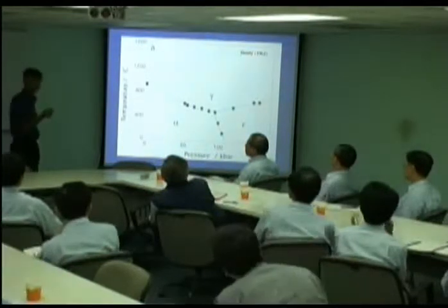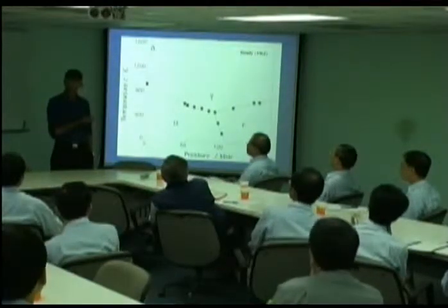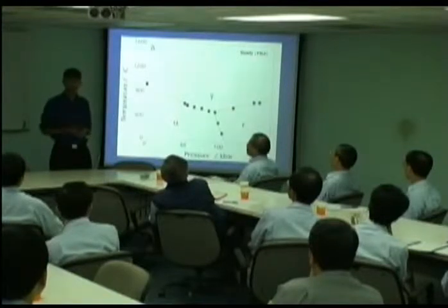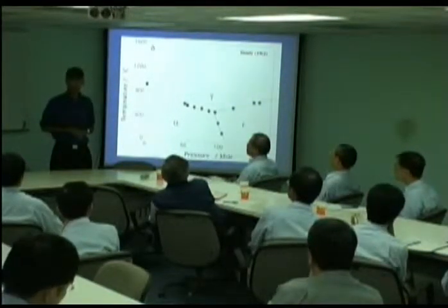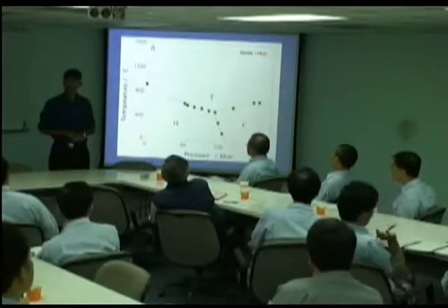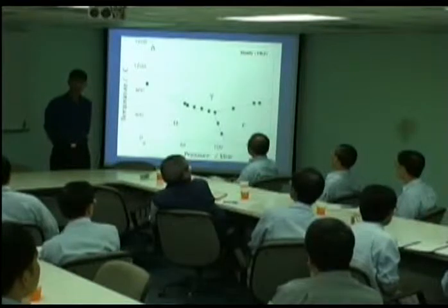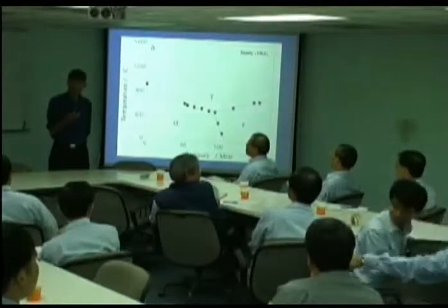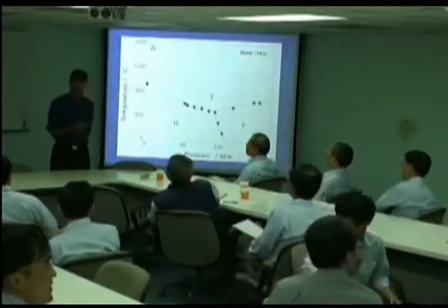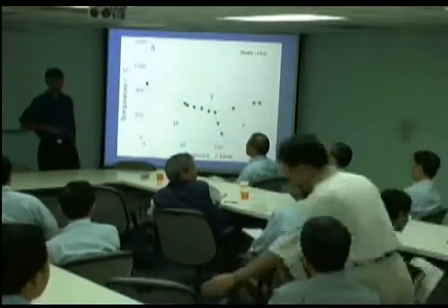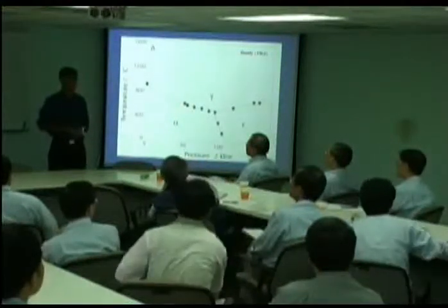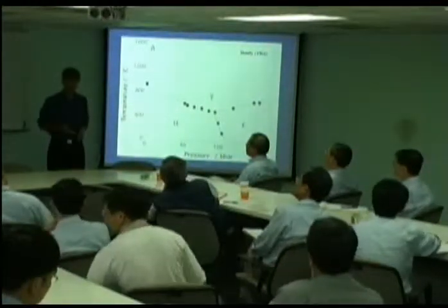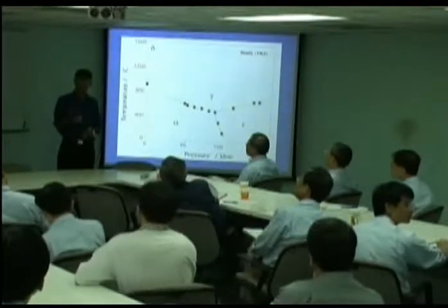So without adding any alloying elements at all, we have three different crystal structures, and each of these crystal structures has very important magnetic transformations in them. If those magnetic transformations didn't exist, then we wouldn't have ferrite at room temperature. We would have hexagonal close-packed iron, and China Steel wouldn't exist, because hexagonal iron has very bad properties, like most hexagonal metals. So magnetism is very important. Now, of course, we start adding alloying elements and make the steel much more complicated, and we can have many different kinds of phases and a huge range of properties as well. That's what makes iron so tremendously successful.